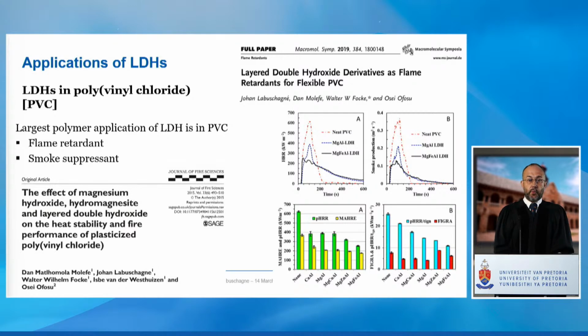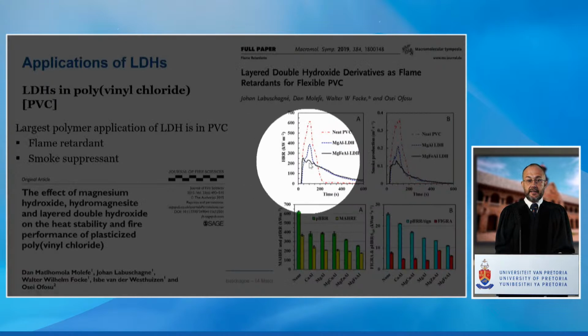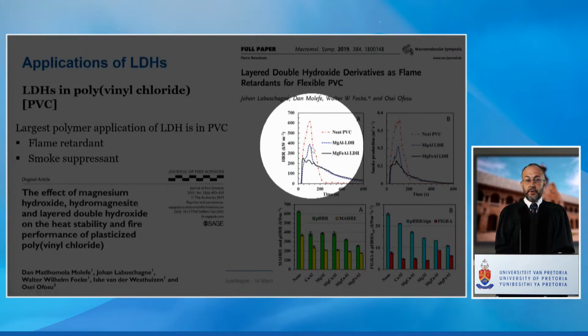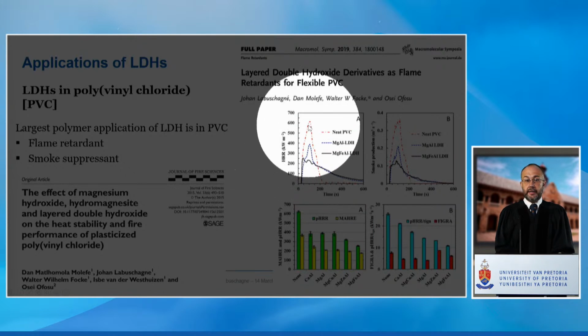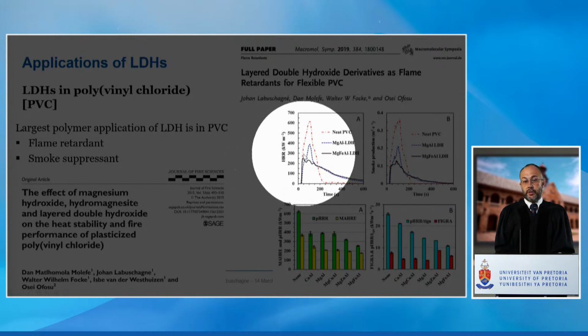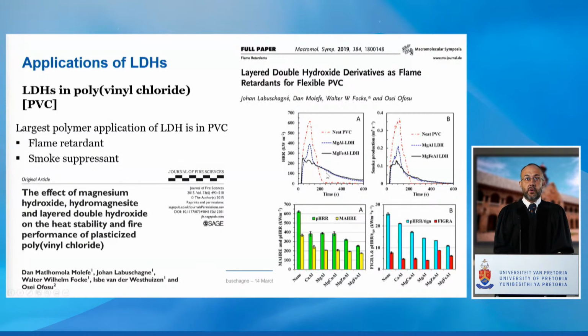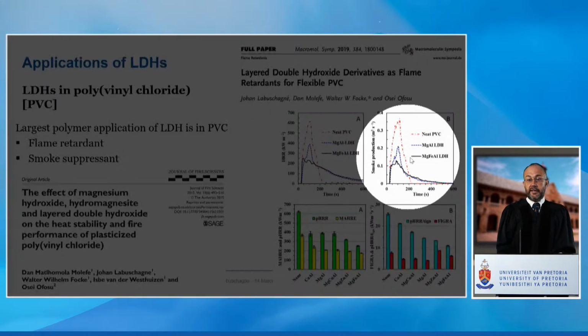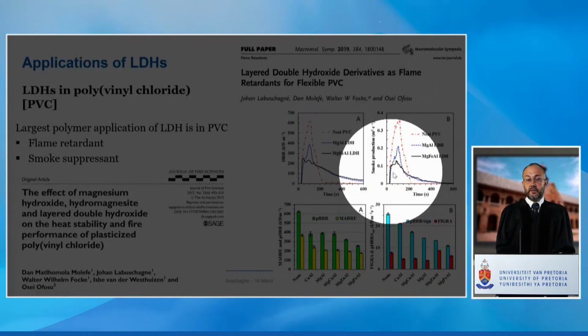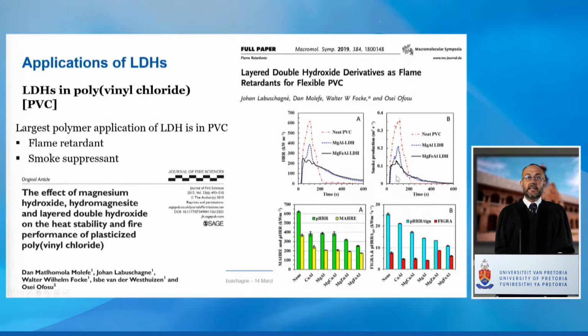The two graphs on the top, one on the left, shows the total heat release rate, and you can clearly see that the neat material burns very quickly and very intensely, so it releases a lot of heat quite quickly. And with the addition of the clay, we drop this heat release rate quite considerably, which is advantageous in flame scenarios. The far right top graph shows smoke release, and we can clearly see that we reduce the smoke release of these polymers, this PVC, quite a lot as well.